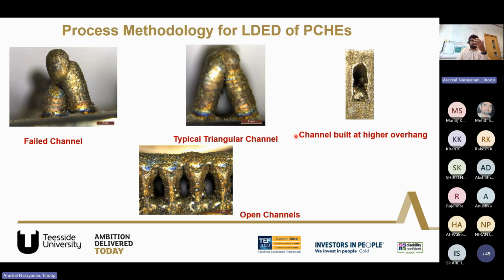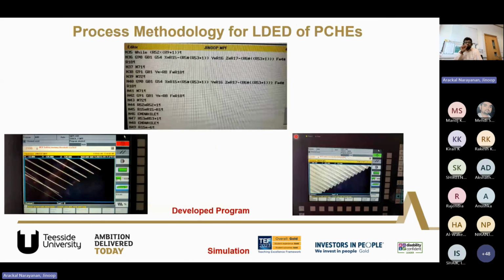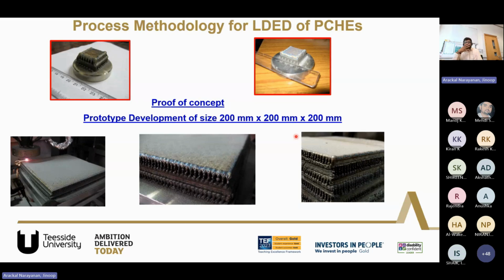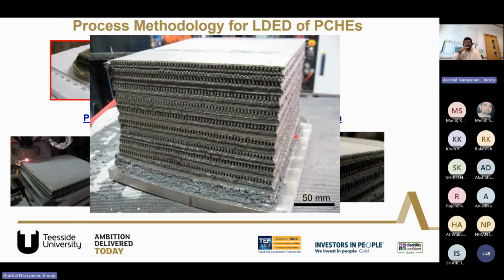And then we made an attempt to make a heat exchanger using a three-axis configuration using DED. It is very challenging to make a heat exchanger with a three-axis configuration. So we did different trials, faced different challenges. Optimizing that sweet spot of process parameters is really challenging. Then we developed the program and the proof of concept, and we built this heat exchanger, which is 200 by 200 by 200 millimeter cube size.